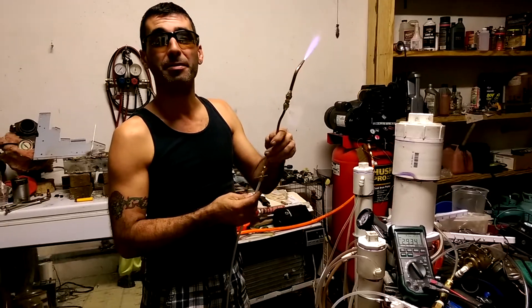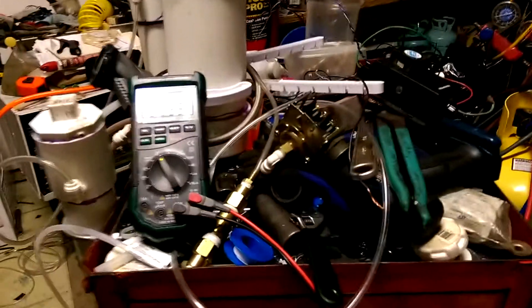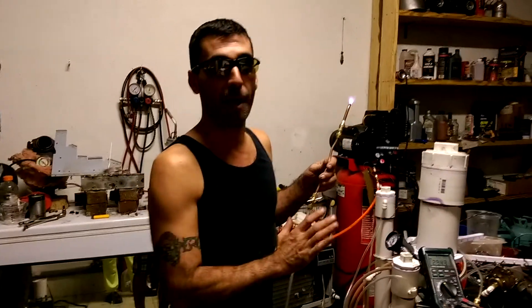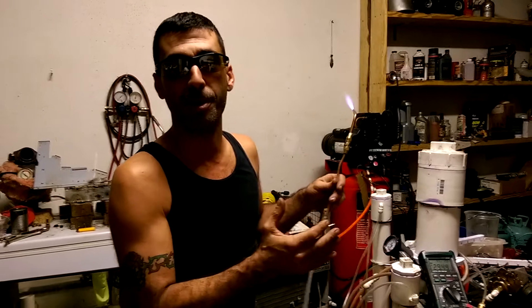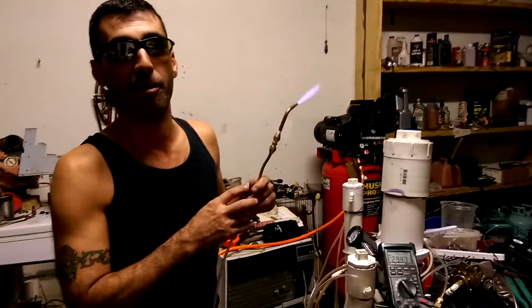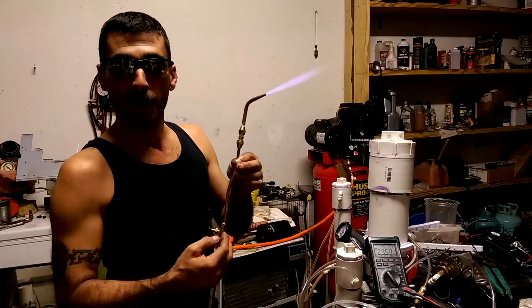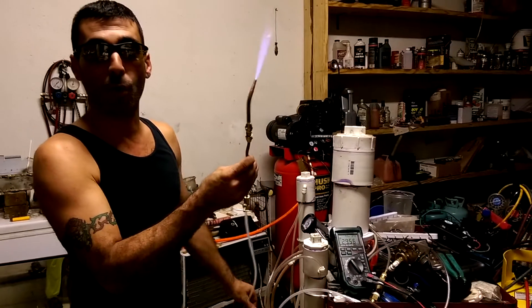As you can see, you can get to a point where my pressure right now is running right at about 5 psi — not too bad. Voltage is getting low right now, we're down to 29 volts, at 29.38 right now. We're having some battery problems, but if you get your voltages up, you'll be able to have a system where even three cells — all three cells are 21 plates apiece — if you divide it to 48 volts, you can have no problem maintaining about 10 psi pressure to do brazing work with. You do have to modify the inside of this part by stuffing it up with some bronze wool or stainless steel wool, as long as it's resistant to corrosion. Other than that, it's not too bad.